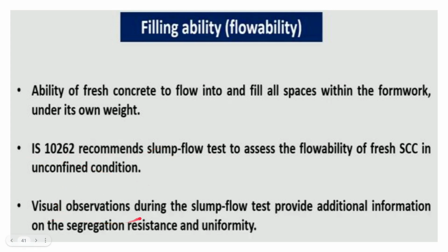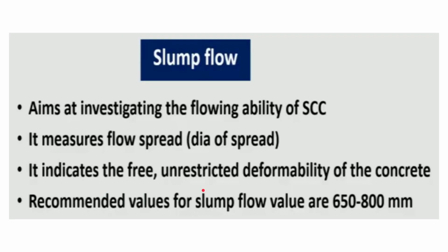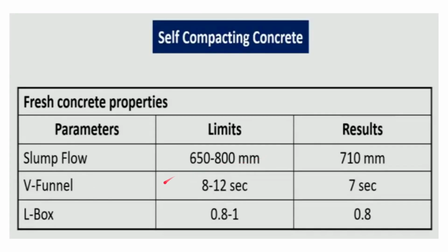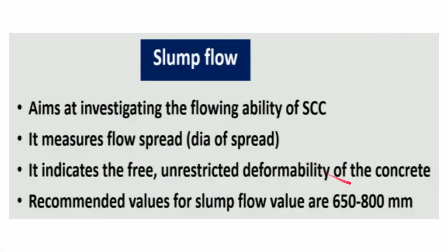Visual observations during the slump flow test provide additional information on the segregation resistance and uniformity. All this can be observed visually during the slump flow test. So what is slump flow? It aims at investigating the flowing ability of SCC. It measures the flow spread, the diameter of spread. It indicates the free unrestricted deformability of the concrete, and it recommends a value for slump between 650 to 800 millimeter, as we saw in the table. Between this range only the slump flow value should be present.